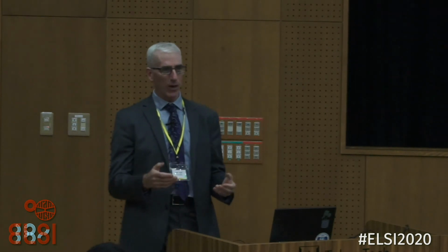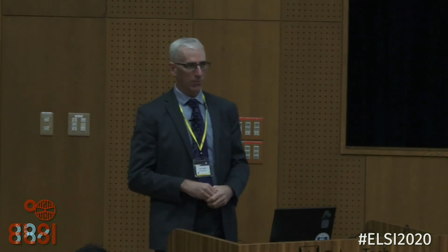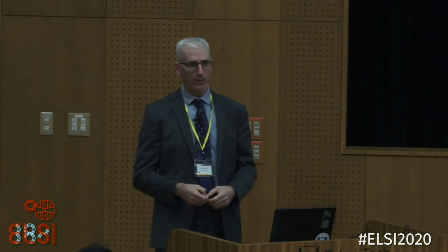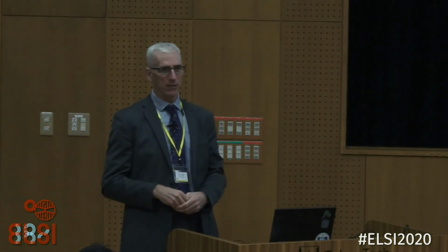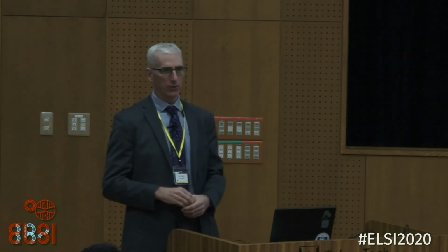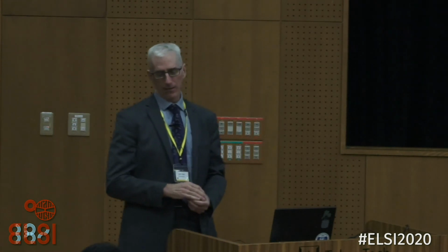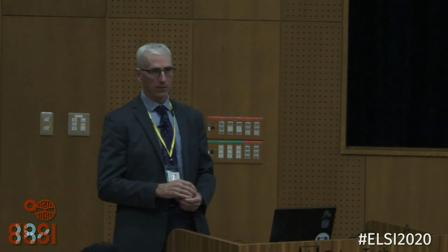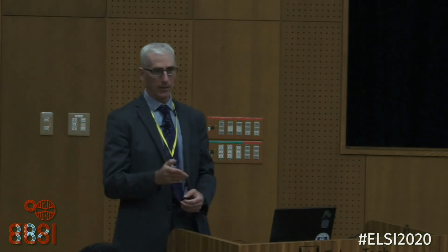It's not the direction I'd like. I'd like to have more control, and this is why I've come here to talk to people who are used to the level of control enzymes have. It was nice to see all those oxygenates. We showed we have an effect, but we'd rather just make one product and know what product we're going to make. We don't have a way of doing that in electrocatalysis besides CO and formate. There aren't things we can make with exclusive Faradaic efficiency in electrochemical CO2 reduction. That's an outstanding problem now since many decades.